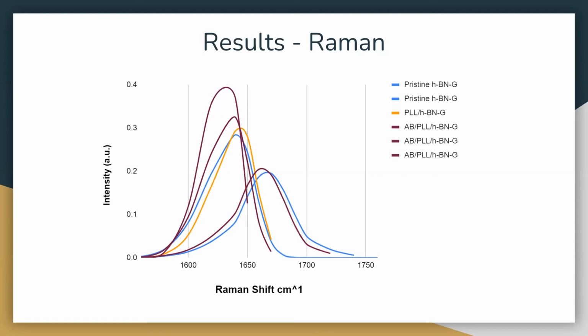Here are my results with regards to Raman spectroscopy of the hexagonal boron nitride on graphene biosensors. Here you're looking at the shifting of the G peak of the graphene in these biosensors. We found that there was only a partial left shifting of this G peak, as opposed to a complete left shifting that's seen in the quasi-freestanding epitaxial graphene biosensors with each additional layer added to the biosensor.